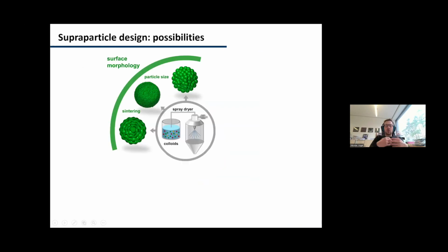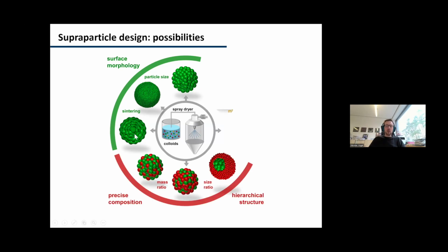Because in a superparticle, you have a lot of degrees of freedom on how to tailor the properties. So for example, you can change the primary particle sizes, which you see gives rise to different internal properties. If we use polymers, we can play with sintering to either strengthen the mechanical properties or also to tailor roughness and porosity and so on. Then we can influence the composition, so we can mix different primary particles, and that gives us, of course, a mixed superparticle. And via changing size ratios, we can even control where these individual particles are in such a superparticle. So smaller particles, especially in fast processes, tend to accumulate on the outside of such a particle.